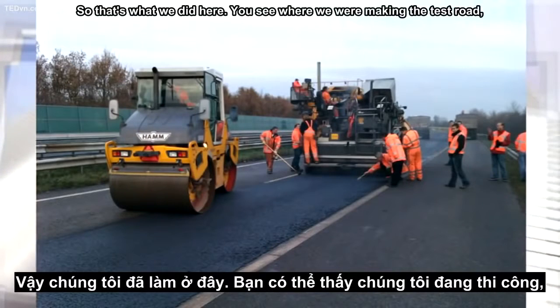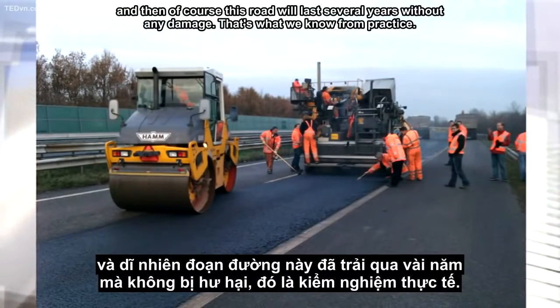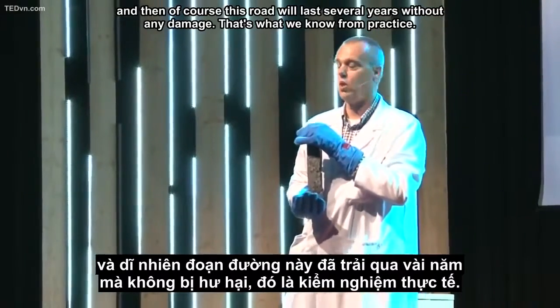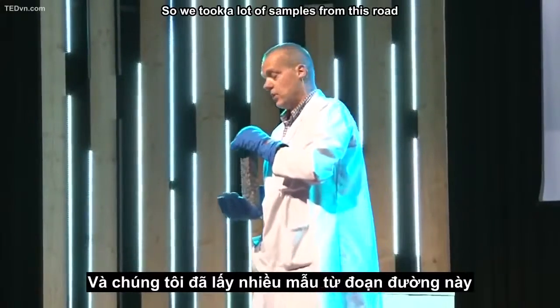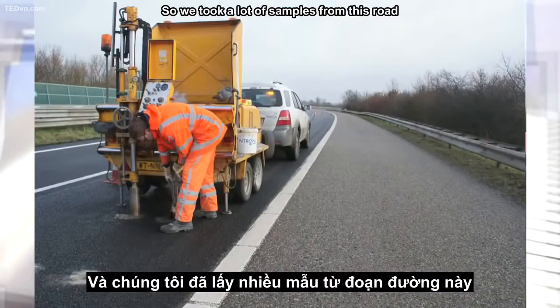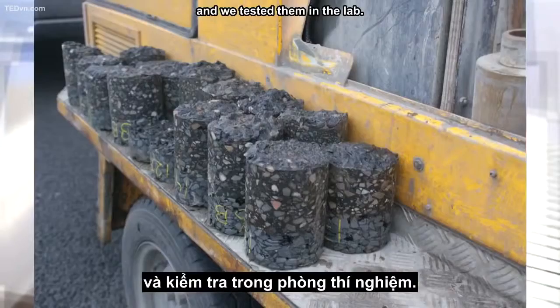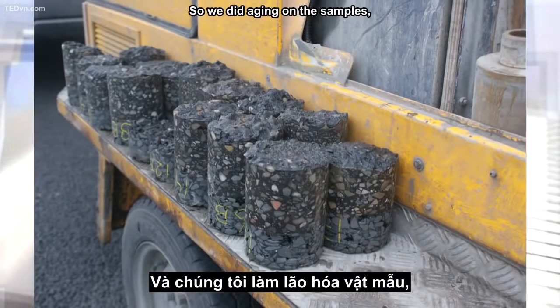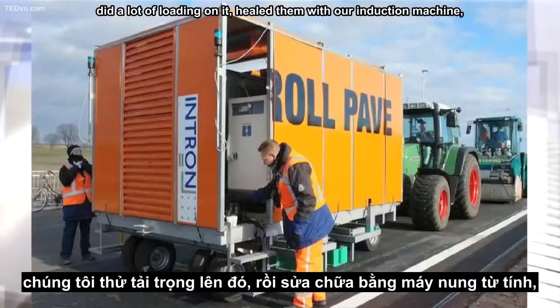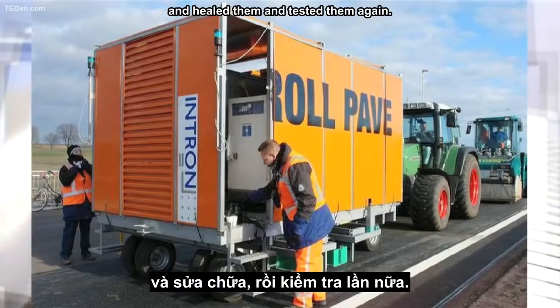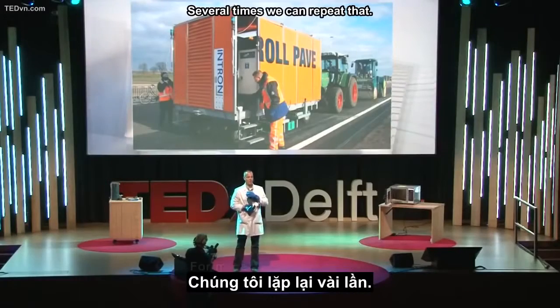You see where we're making the test road. And then, of course, this road will last several years without any damage. That's what we know from practice. So we took a lot of samples from this road, and we tested them in the lab. So we did aging on the samples, did a lot of loading on them, healed them with our induction machine, and tested them again. Several times we can repeat that.